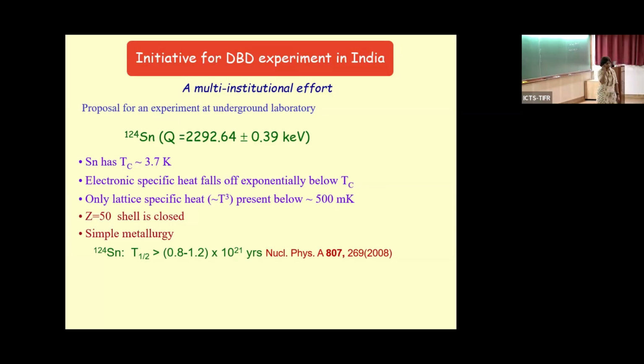Now tin goes superconducting at low temperature, with a transition temperature around 3.7 K. What happens when it goes below the superconducting temperature is that the electron specific heat, which goes as gamma T, falls off exponentially, and only the lattice specific heat will survive, which is T cube. Now if you are at a temperature below 1 K, the T cube will be much smaller, and hence you can make it into a calorimetric detector.